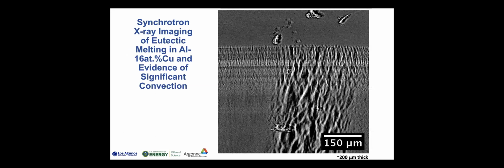I'm going to show one more example. This is another example, in this case for melting of metallic alloy. So down below, here we have an aluminum 16 atomic percent copper alloy, and we have one of these lamellar eutectic structures. Below is solid, and here we've actually stopped a planar solid liquid interface in the field of view. Up on top is the alloy melt, and we're going to do a directional melt from the top down, and you'll see some interesting phenomena that occur.